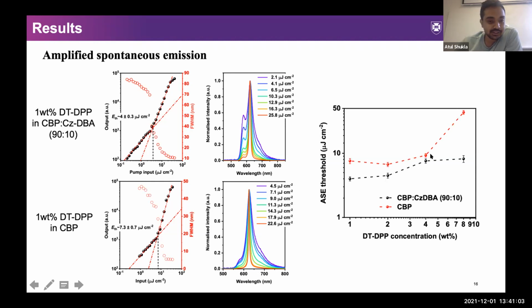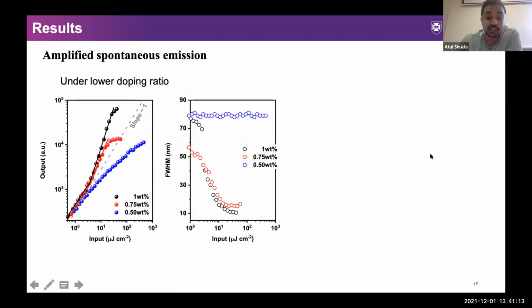Now, another question that usually comes up is, what happens if we reduce the doping ratio of DPP? In order to study that, we did ASE measurements for different lower doping ratios. This figure shows the input-output curves. As we see for 1 weight %, we see similar thresholds as compared to 0.75%. But we find that there is a difference in the saturation intensities, which is an indication of increased bimolecular quenching in these systems. And for 0.5%, we do not see any light amplification. It deviates from the slope 1. That is again because of increased bimolecular quenching processes.